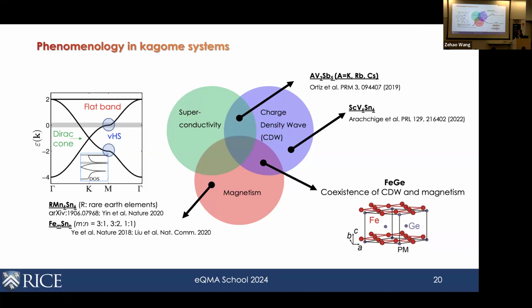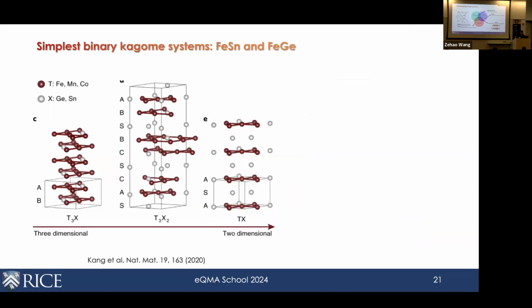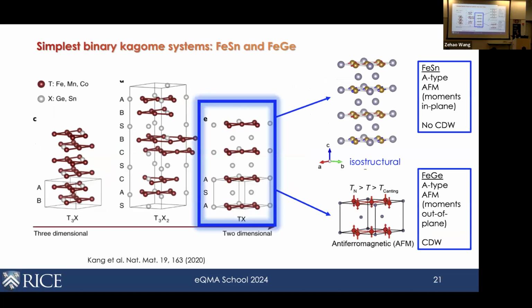Okay. So with this in mind, I want to first look at the simple example of systems that only exhibit magnetic order and discuss the question whether this flat band, when tuned to the Fermi level, can give you a Stoner type ferromagnetic order, right? So to do this, we are looking at the simplest binary Kagome systems, iron tin and iron germanium, and you can have different kinds of stoichiometry, but I'm going to focus on the simplest one, which is the 1-1 system.